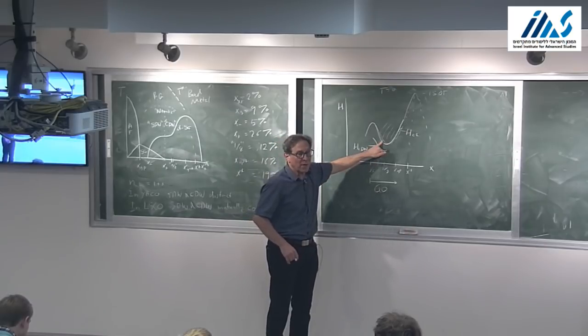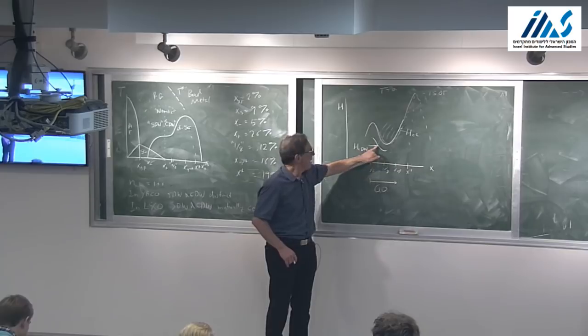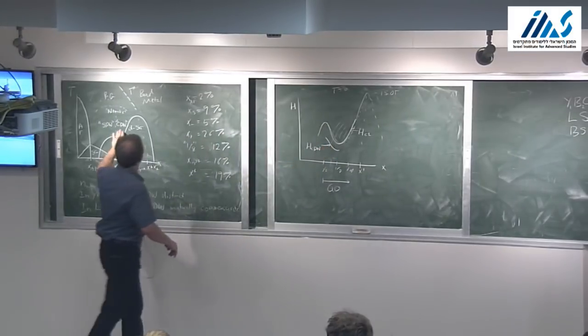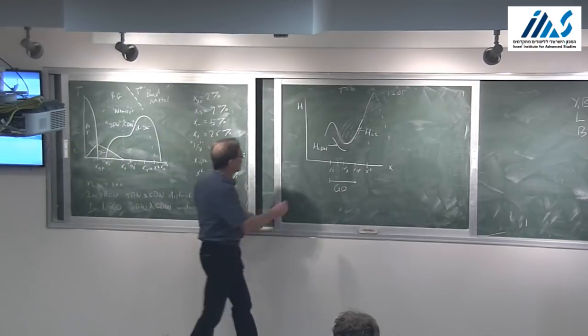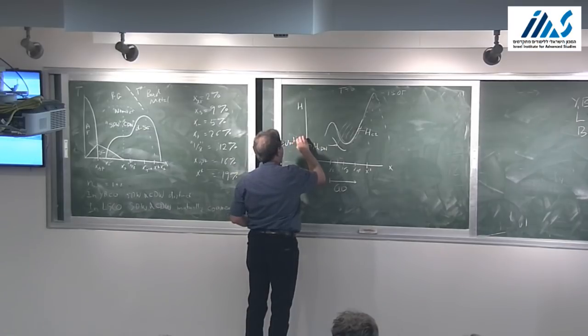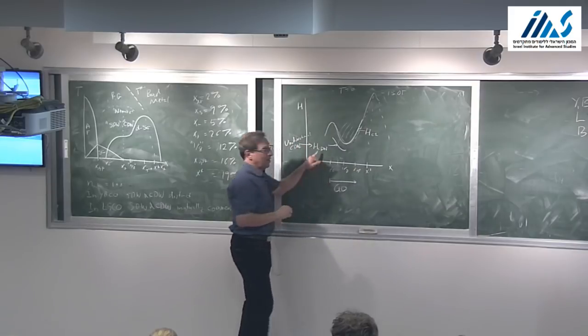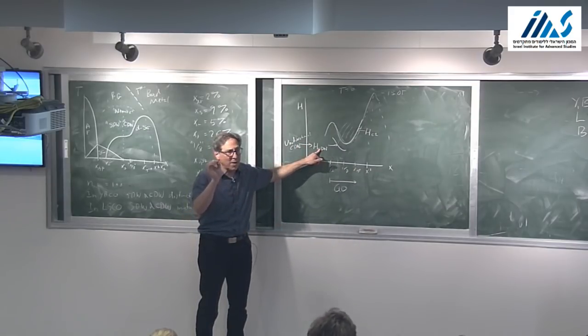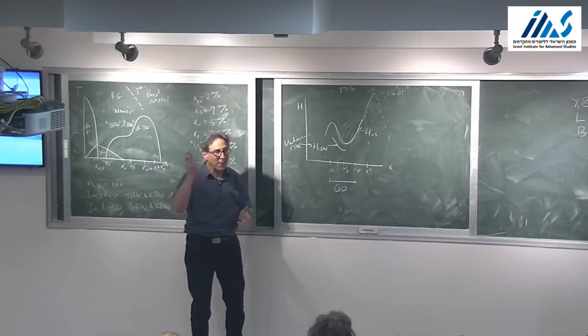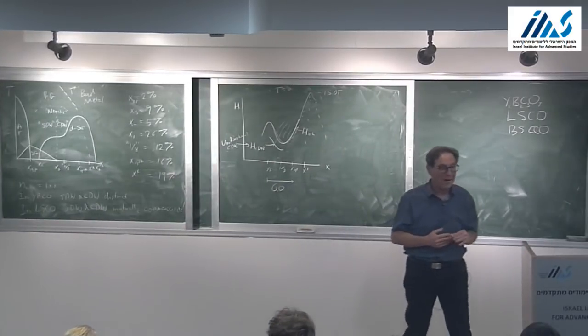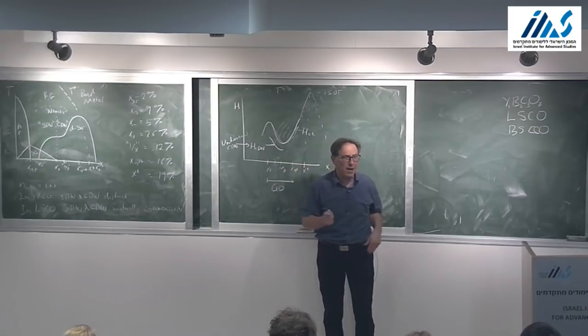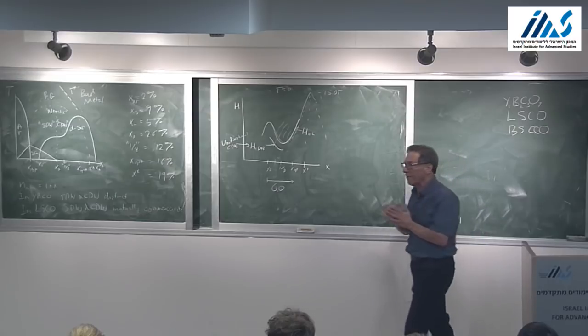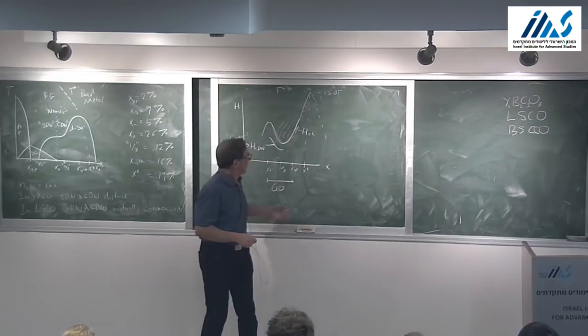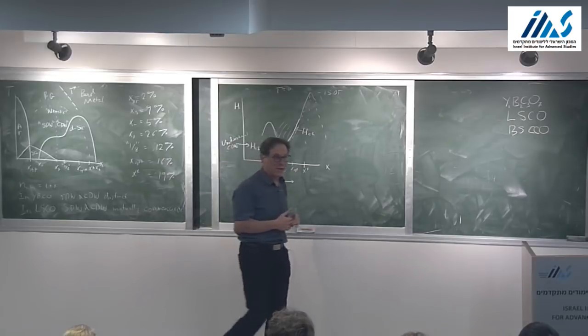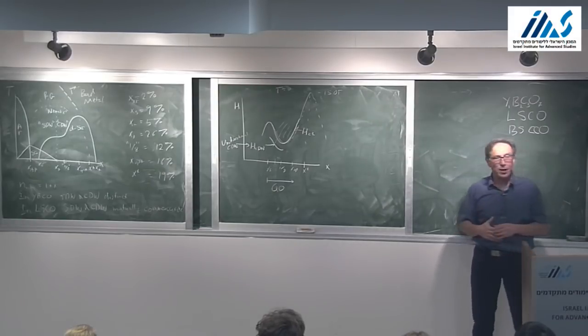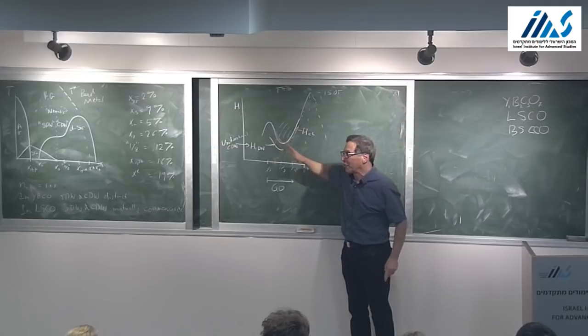Here, there's something that looks an awful lot like a phase transition. So, first place, the charge density wave correlations here have some differences with the charge density wave correlations here. Here, the charge density wave correlations are unidirectional. And so there is a peak that comes up. It's a three-dimensionally ordered peak that comes up with a field dependence that looks like the field dependence of an order parameter. There are also ultrasound experiments that detect a thermodynamic phase transition at the same value of the field. So I suspect that this isn't actually a phase transition on theoretical grounds, but on empirical grounds, this looks operationally like a sharp phase transition. So that's why I've drawn it as a sharp phase transition.